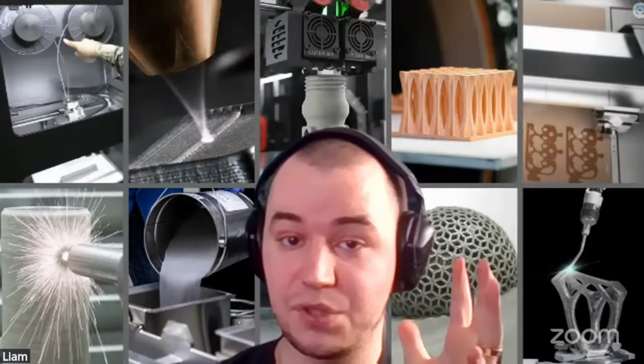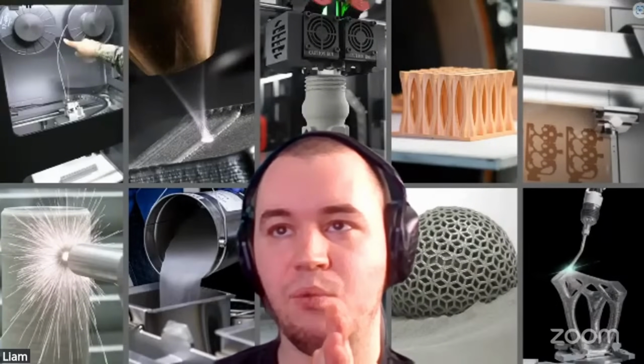Okay, you have this powder, and then you have to have it in the oxygen poor or oxygen free environment before you can, layer by layer, go with the laser and heat it up so the particles get attached together, correct? Yeah. So what you're doing is you're creating a very small melt pool, and this is not the same as cold welding, because cold welding is a good indicator of where there is and is not an oxide layer present.